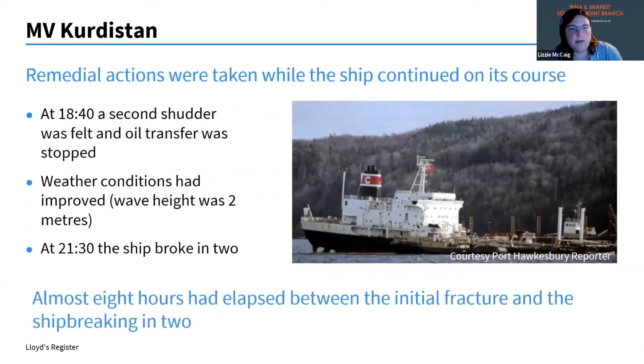The crew took remedial actions, and the ship continued on. They did things like transferring oil from number 3 wing tanks to number 4 tanks, but then they felt a second shudder, and they halted that oil transfer. The weather conditions had improved by this point, but by 9:30 the ship had broken in 2. Basically between the first fracture and the ship breaking in 2, it was about 8 hours. So it was quite quick.